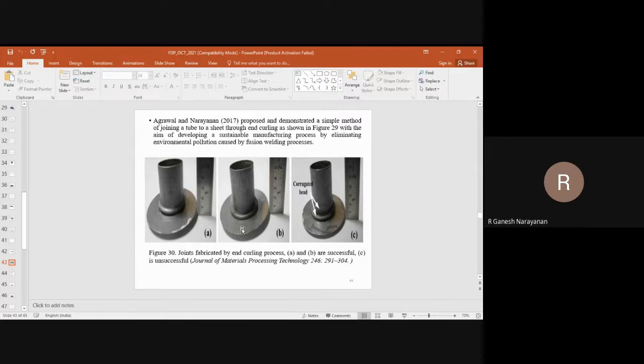If you use fusion welding, both will have change in properties. If you use friction stir welding, again, both will have change in properties. But these two structures are perpendicular to each other. I don't know how you will go for friction stir welding. Maybe it's very difficult. Laser welding is possible because it is non-contact. For friction stir welding, you have to design a specific tool for that. But here, you can have a simple die and punch. Simple machines like a UTM can be used, and locally you deform the material, one material only, the tube, and you can join these two structures. This is also a tailor-made structure.